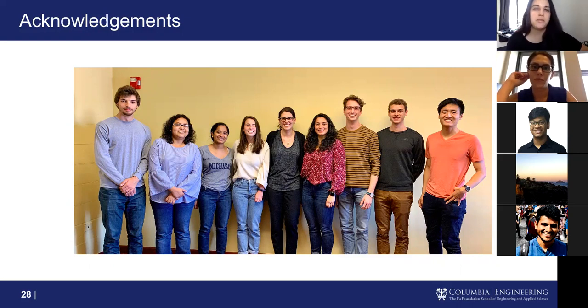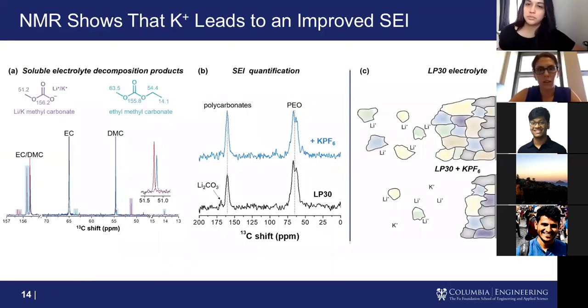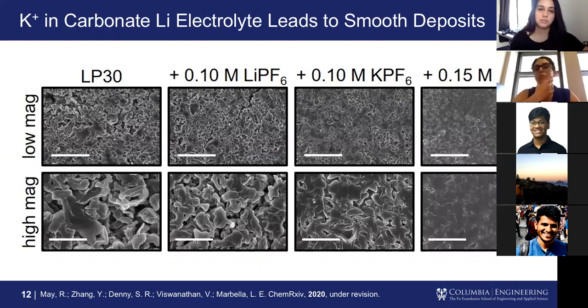And this one, I believe, was in regards to slide 12 to 13. It says, when those experiments, at what duration were the tests being done? Let me go to slide 13. Okay, so these experiments were done at a polarization of 1 milliamp per centimeter squared for 2 hours. So we were just depositing for 2 hours.